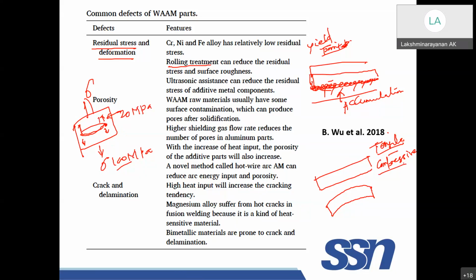Compressive is desirable. To understand it, I'm putting the same example. If it is a compressive residual stress of the same 20 megapascal, the tip now sees 80 megapascal. Though you are applying 100, the tip only sees 80, because this is minus. So there will be crack closure. Instead of crack growth, crack blunting will happen. So always in a structural member, tensile residual stress is not good.